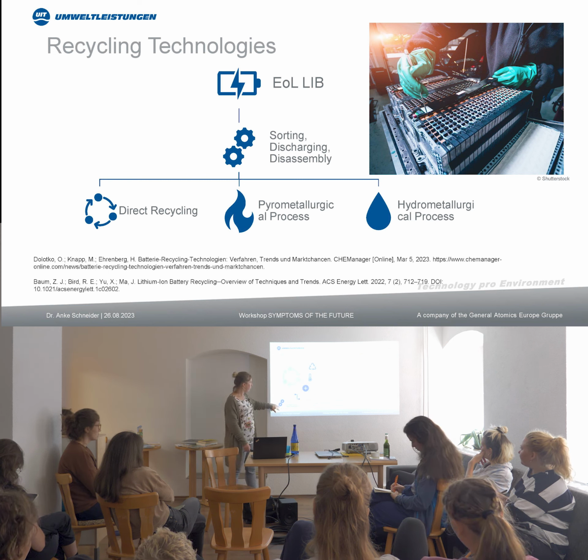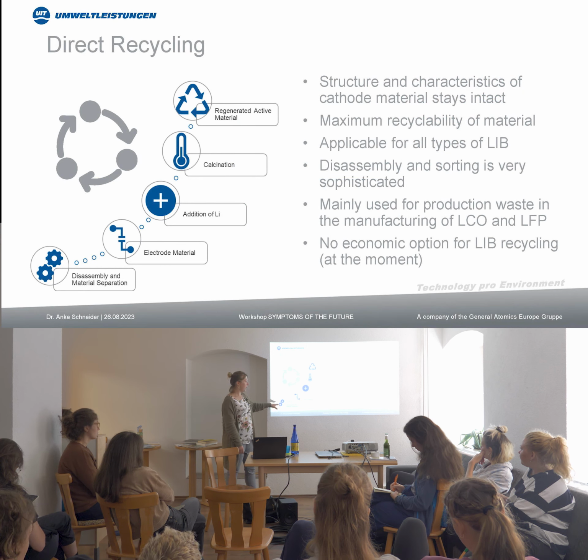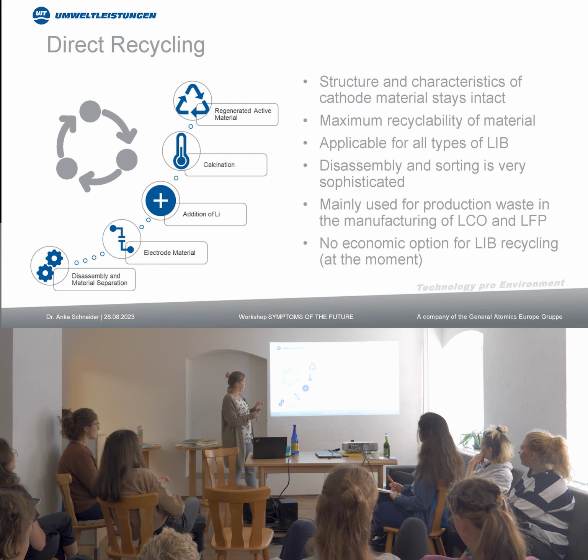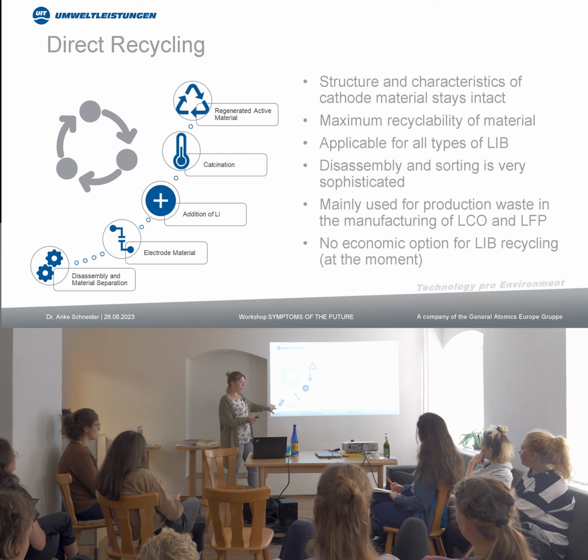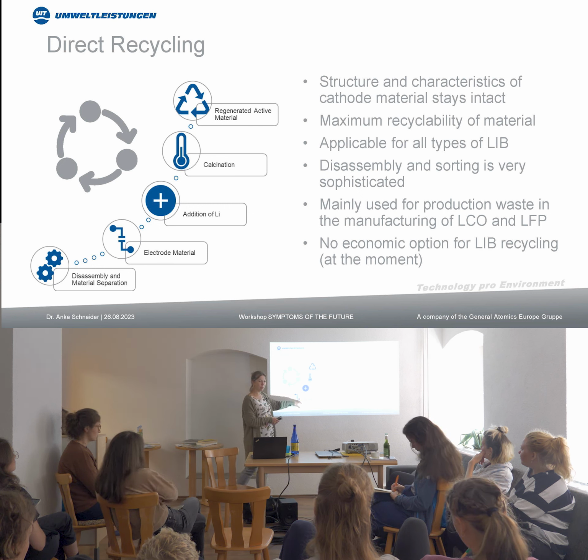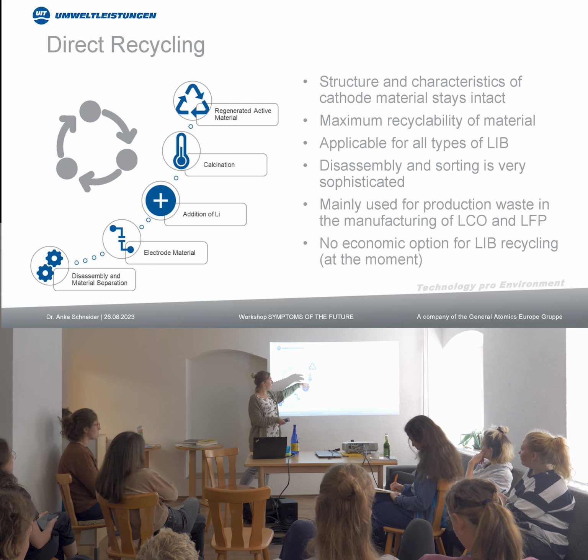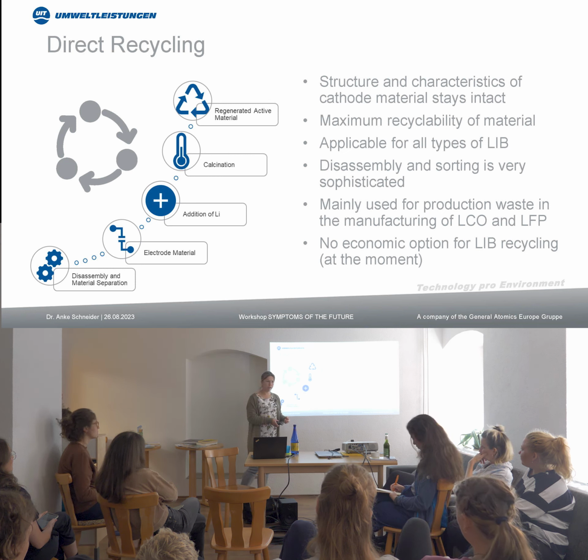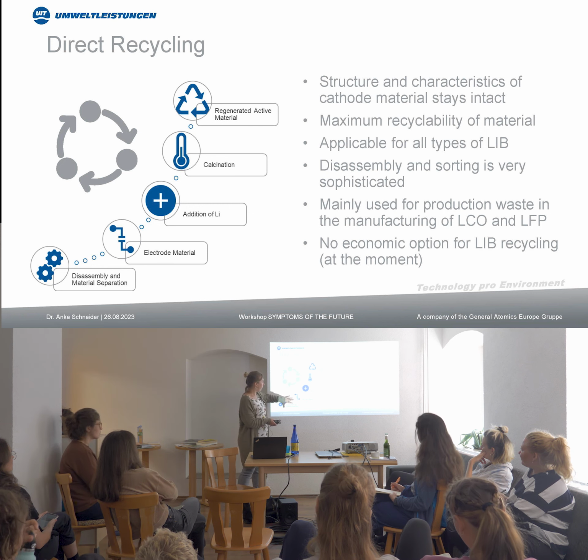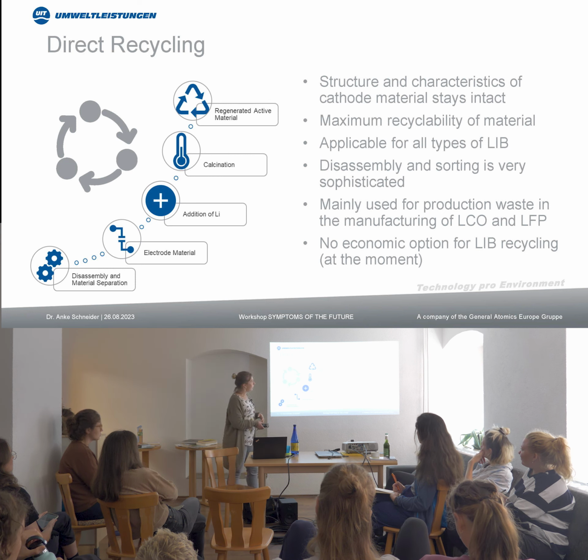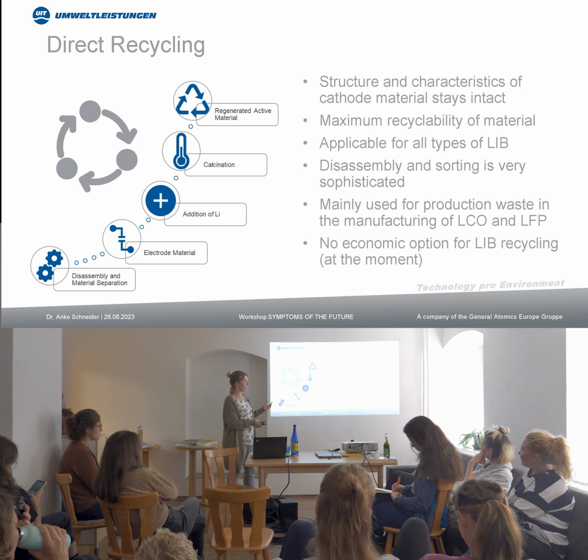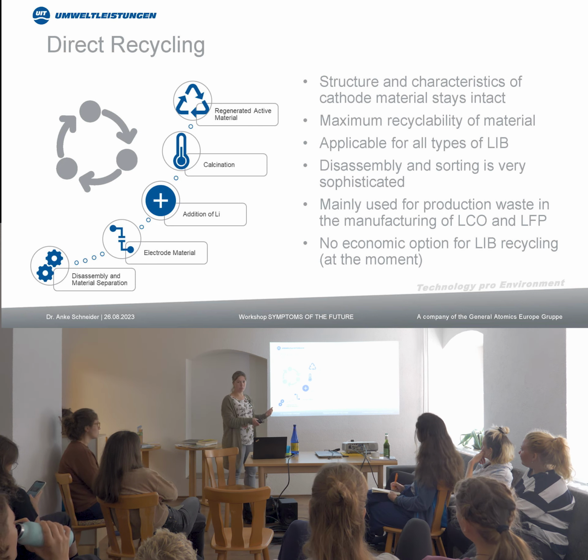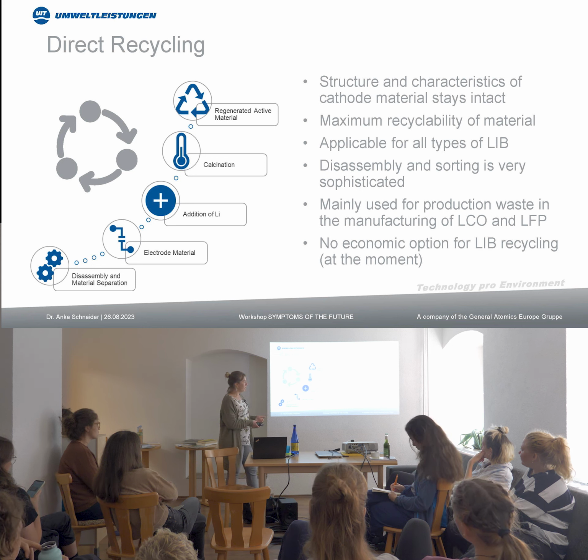Direct recycling. If we start with direct recycling, we need to disassemble and separate the materials very clean and very sophisticated. So this is a very, very important part for direct recycling. Then we get a pure electrode material, so in best case, a pure powder of a cathode material. After we have this, then it's quite easy actually. We just add some lithium salt to it, we put it in an oven, and afterwards we have a recycled material. So this is actually, as I said, quite easy. However, this part is very challenging. In general, with this direct recycling, the structure and the characteristics of a material stay intact, and you just regenerate the lithium content of it. It has a maximum recyclability of material, so it's great. It can be applied to every type of battery.